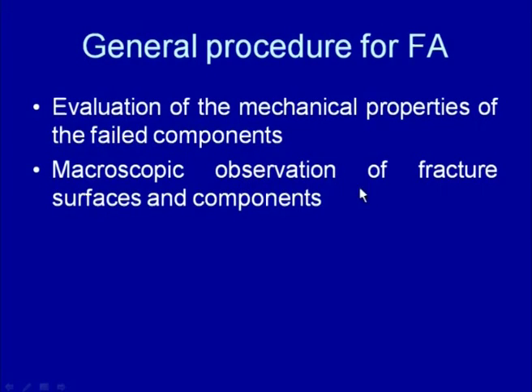So the macroscopic examination will give us an idea about where fracture has taken place, which location has acted as the site of stress concentration and weakness and has triggered the fracture. At the same time, this will also show the initiation site, the fracture initiation location from where fracture has initiated, and then in which direction the crack has grown.